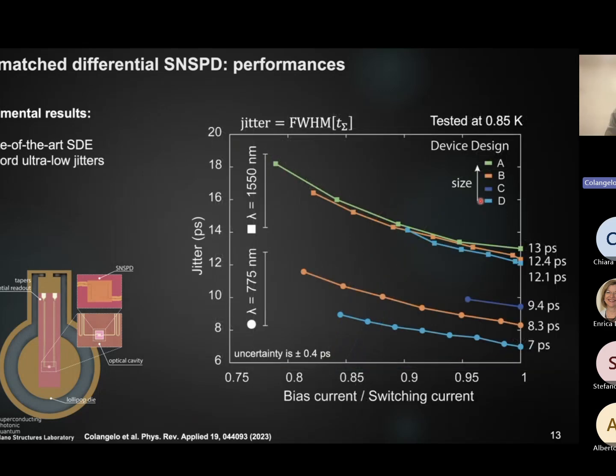The big deal is that when we instead test the jitter, each device design converges below 15 picoseconds. So independently of the large area, we are getting more or less the same number of picoseconds in the jitter, around 12 to 13, meaning that our differential design and impedance matching design is actually working to compensate for these intrinsic issues. And most importantly, when we test at 775 nanometers, we break the 10 picosecond barrier, which was believed to be impossible for a large area device. So this is still an unbeaten record in the community. And so we're able to merge in the same design a very high efficiency and a very low jitter, which is very good for all the protocols requiring high performance.